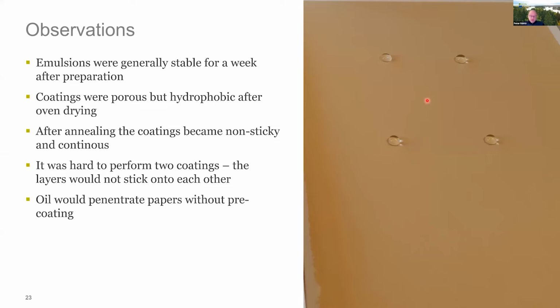After the first drying step, the coatings were quite hydrophobic, but there were also pores. So after annealing, we actually get rid of the pores, and we also get a non-stick continuous film. We weren't able to produce two coatings. They wouldn't stick to each other for some reason. And if we didn't have the pre-coatings, we would have problems with the board, as we would have the oil penetrating it.